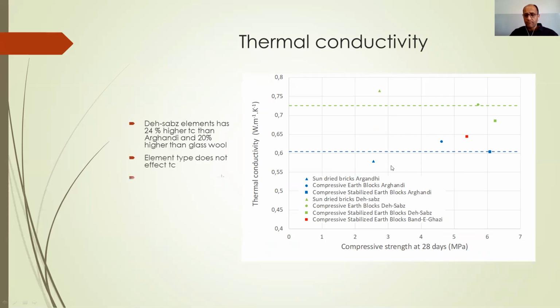The thermal conductivity, as we can see, this dashed green line shows the thermal conductivity for Deh-sabz, which is 24% higher than Arghandi, and it's 20% higher than thermal conductivity of Bandeghazi. Whatever the element type is, it's not really affecting the thermal conductivity of this soil. And we also can see that since the thermal conductivity is high, we need to develop a prefabricated panel mixture of soil and wheat straw to use for the external walls to prevent this thermal conductivity.